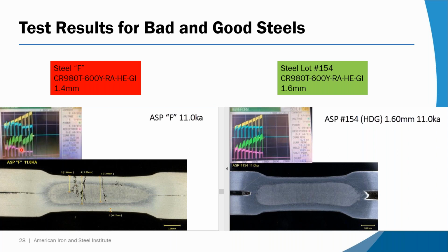That power drop probably signifies the end of nugget growth, because at a lower power, your power by definition is less. Your nugget pretty much stops growing when that happens. Although we are continuing to upslope, so it is trying to recover and resume.